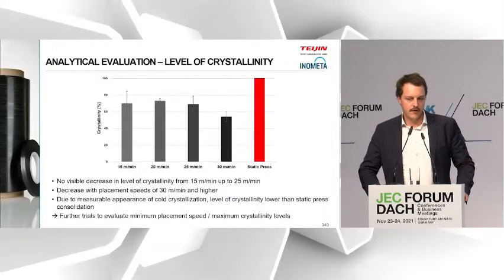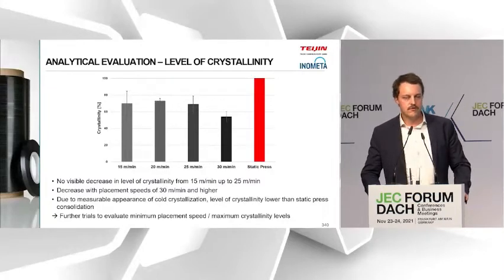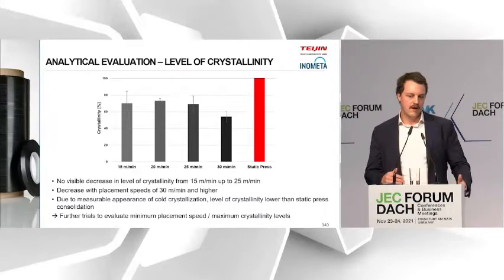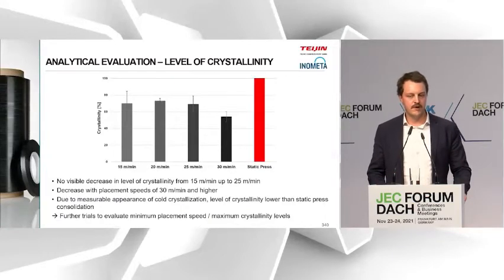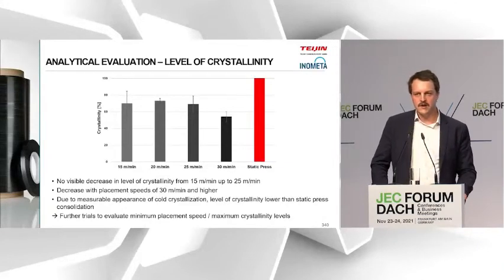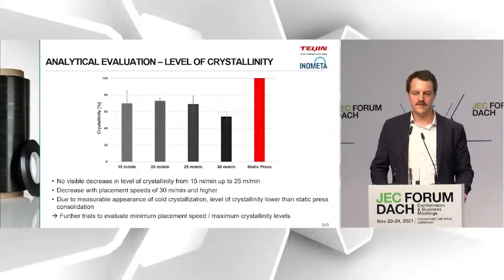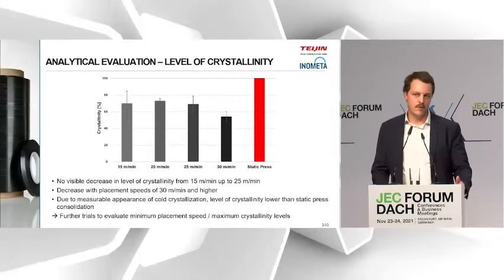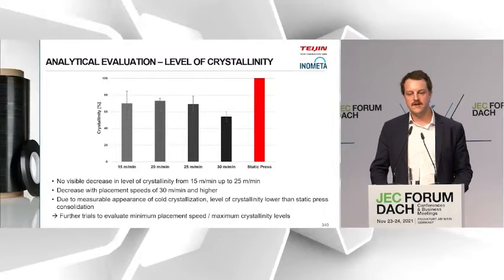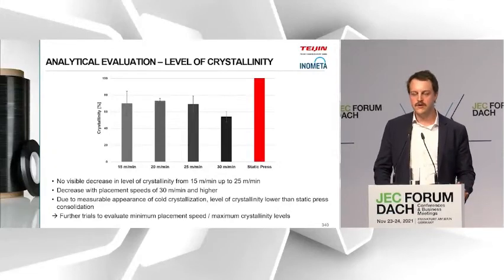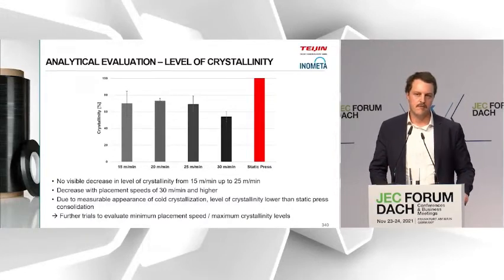We did that comparison as well for the different speeds shown for the microscopic analysis. Here you see, if we look into the first three, the 15, 20 and 25, if we take into account the variation in the results, we could say they're all on the same level. So that's all in percentage to the fully crystalline sample from the static press on the right. And if we increase the speed even more, we see a decrease in the final crystallization level. But nevertheless, it's not on the level where we want to be, because we want to have the best possible mechanical properties and find the right setting for each material option. Therefore, now we are also looking into other speeds and adjusting based on the polymers used in the different tapes.